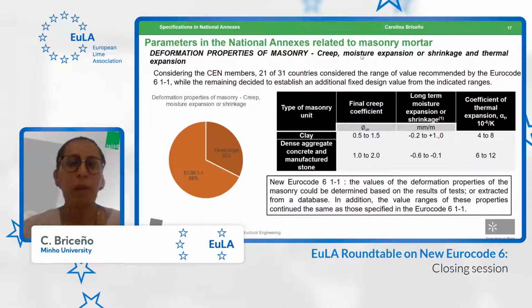Finally, there are the parameters related to the deformation properties of masonry: creep, moisture expansion or shrinkage, and thermal expansion. In the standard, in both versions, it is indicated that these values can be determined based on the results of tests without specifying any standard to be used, or could be taken considering the table shown in the standard, which is the one shown in this slide. 68% of the countries consider the ranges shown in the standard. Meanwhile, the remaining 32%, instead of considering a range, consider a fixed value regarding the constants associated to the final creep, the long-term moisture expansion, or the coefficient of thermal expansion.